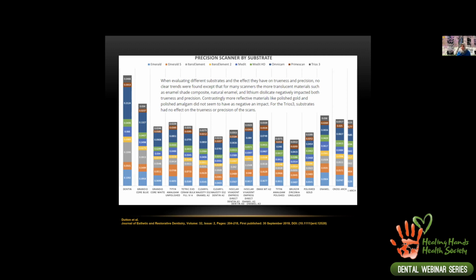That might be one thing to keep in mind if you're trying to find one scanner that has a more broad application. But I think it's an important finding to look at, especially from a partially edentulous perspective, because of all the prosthetic appliances that we do, it is one appliance that's probably going to be affected by this study more than any other study, because your appliance is going to have to sit perfectly on all these different substrates. So their conclusion was that specific substrate could have a dramatic effect on the trueness and precision. So that's something that we have to keep in mind.